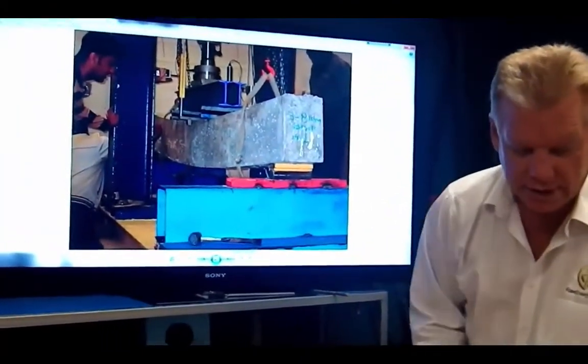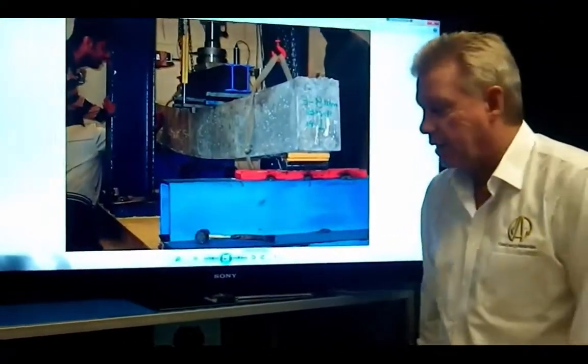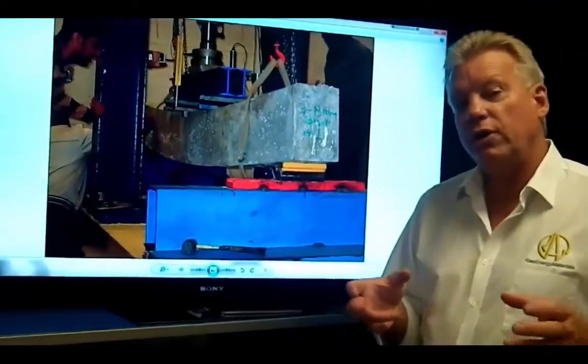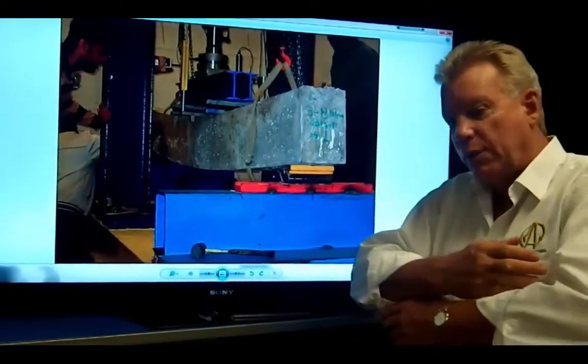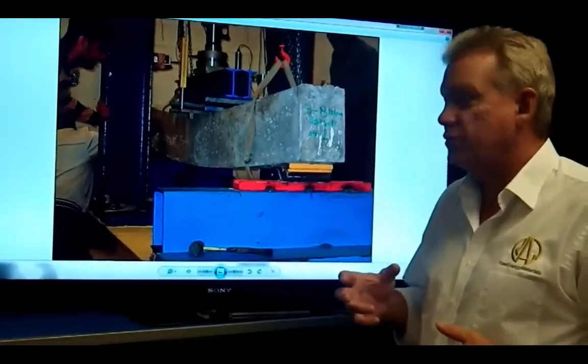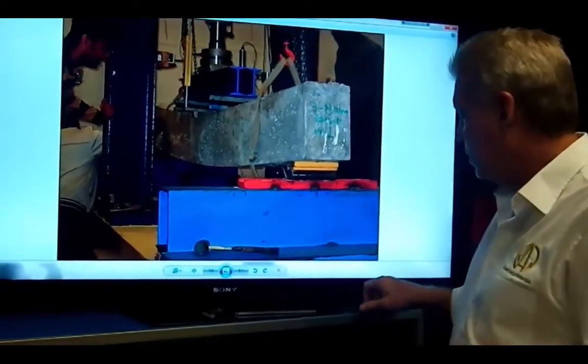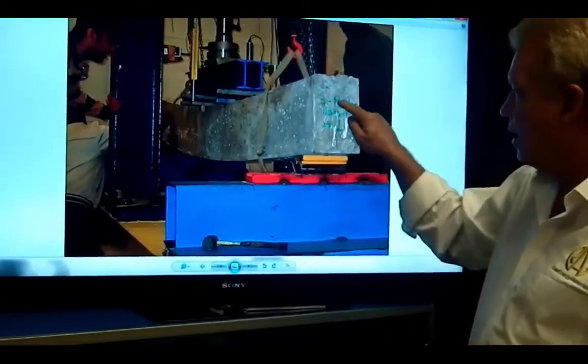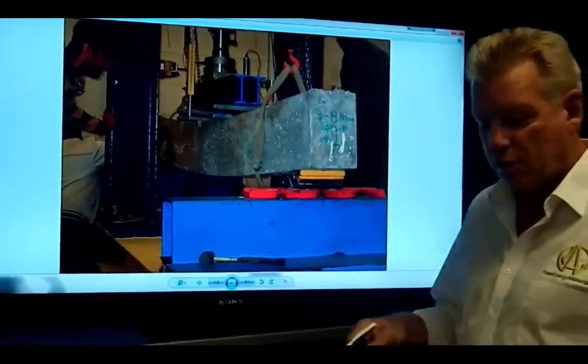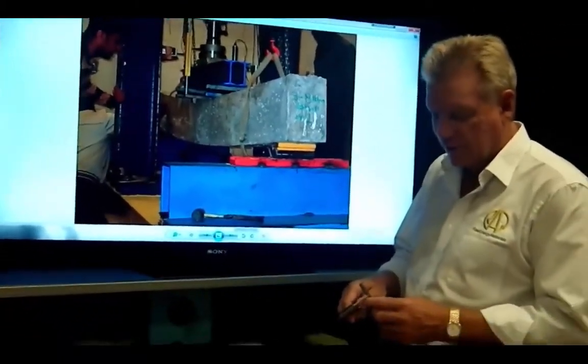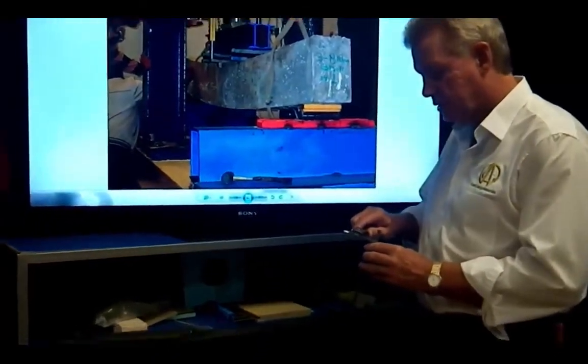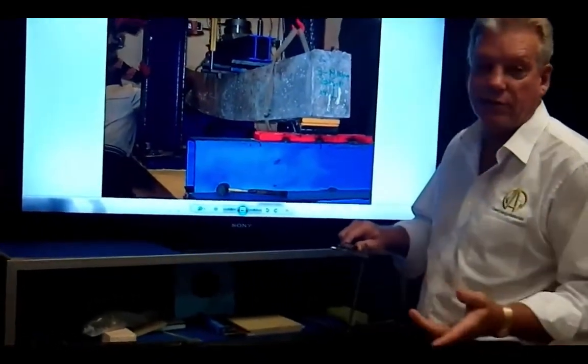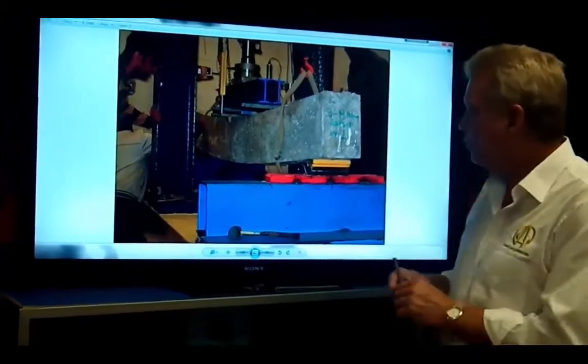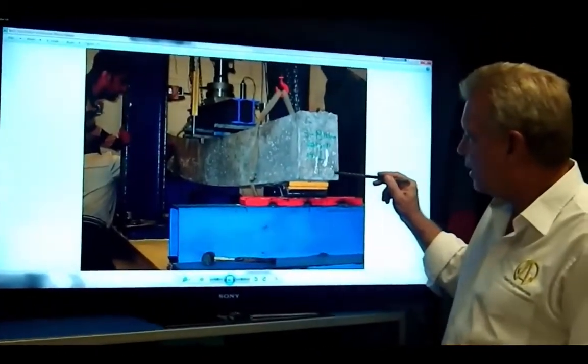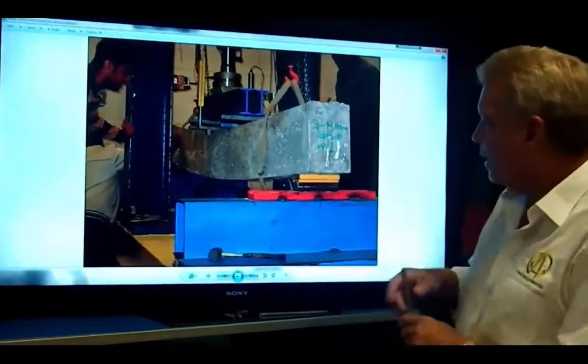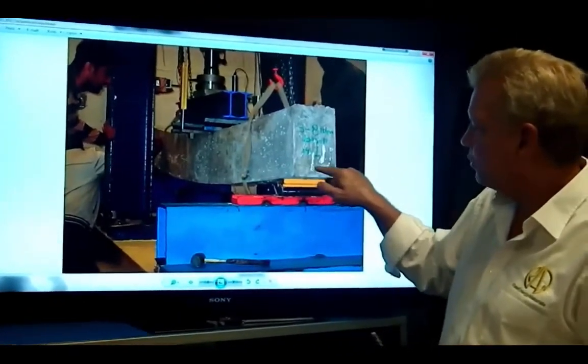On the screen here is a beam test that goes a little ways to showing you the potential that rock rebar has to stiffen something in its tenacity. This beam has 3 pieces of 8 millimeter. 8 millimeter is a little smaller than number 3. Number 3 is like 375 thousandths of an inch. This is 315 thousandths of an inch. And 3 pieces of this are buried in this thing, 1 inch from the bottom, middle, and an inch from each edge.